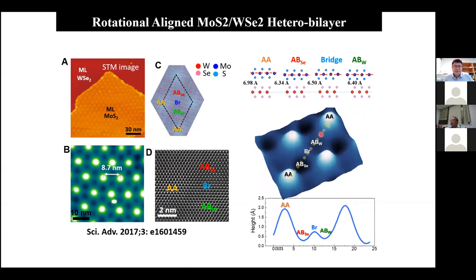Now let's look at this first moiré pattern being observed in the transition metal dichalcogenides. This is one we saw in 2017, and MoS2 has about 4% smaller lattice constant than WSe2, and you will see this moiré pattern very nicely. The periodicity of 8.7 nanometers is precisely what you expect if you assume they have a rigid rotation, without any reconstruction. But there's also an ambiguity: whether they are 0 degree or 60 degree, which gives you the same periodicity. So we used the Cs-corrected TEM to later confirm that what we observe is what we call R stacking. That means it's 0 degree.